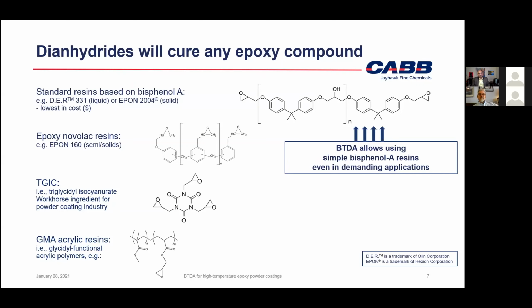type resins. What's different about BTDA is that a formulator can choose BTDA and use it with a standard bisphenol A-based solid epoxy resin, a simple di-functional epoxy resin, and you can get high performance, a very high degree of cross-linking from that system, just because the BTDA works in it differently.